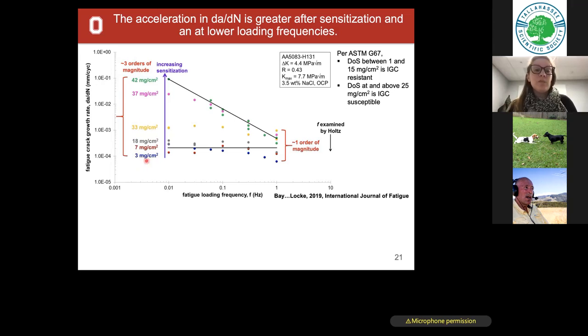And what you see is as you raise that number, crack growth rates don't do a whole lot initially. In a middle range, they start to increase, but we're still frequency independent. But when you get really sensitized, these really high degrees of sensitization values, meaning I've changed my metallurgy quite a lot in a not great way for corrosion, you see that we get this very steep frequency dependence.